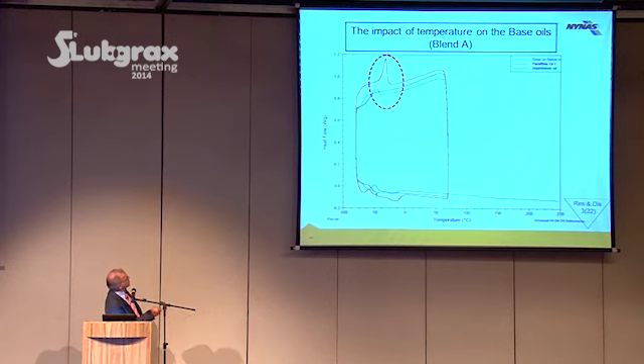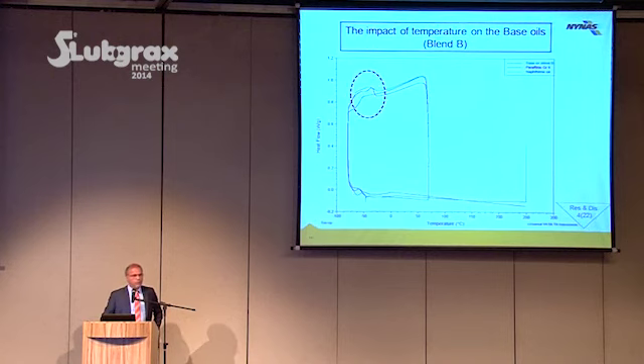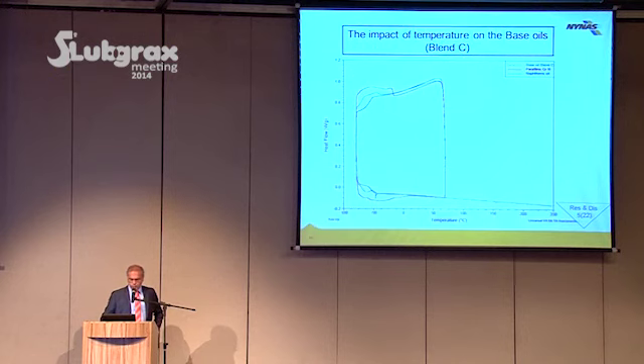And when we mix it, we reduce the impact of that wax, or we postpone the creation of the wax to a lower temperature. This is thanks to the high solvency power of naphthenic oil, so it dissolves the wax. We see the same for group 2 and group 3, which I don't go through.